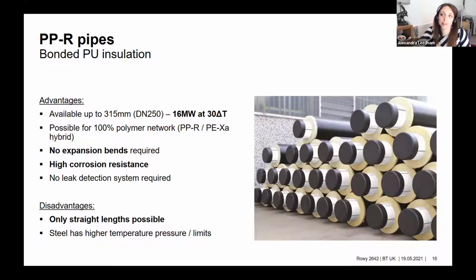So at a temperature difference of 30 degrees, for example 70-40, you would achieve 16 megawatts covering in a 315 mm pipe, so quite a large amount. There are no expansion bends required due to the way the material expands and contracts. So as opposed to steel, this pipe can go just in a straight line without any need for the loops.